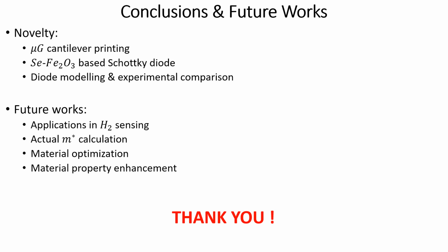Development on printed material optimization is promising as the microgirder technology is capable of printing incompatible organic and inorganic materials onto substrates. Apart from new material investigation, we also need to enhance the material properties to improve the interface characteristics of these materials with metal-metal contact. These processes can potentially bring down the ideality factor of the devices fabricated using this technique.